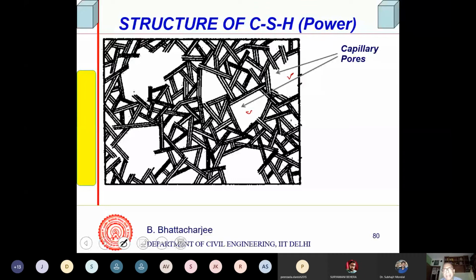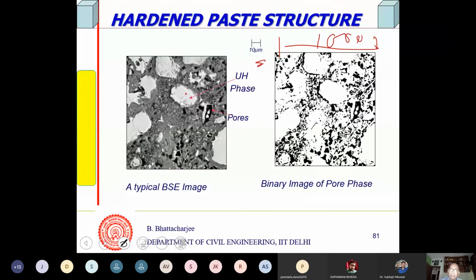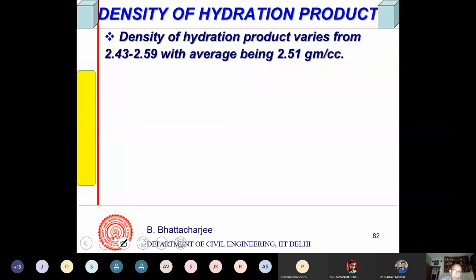And you can see a typical backscattered electron microscopy image also. This is 10 micron, so 100 micron. If you look at 100 micron size, you'll find unhydrated cement which will look white. Pores will look black because backscattering doesn't occur from pores, so they're all black. And the rest are gray. Hydrated phase is gray.